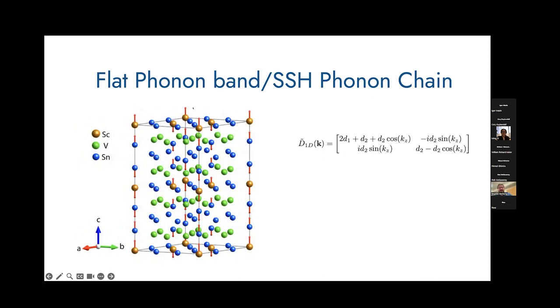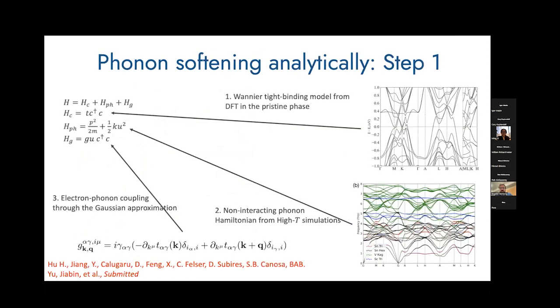Okay. After. So the model here is that of an SSH chain, basically. So it's very flat in plane, but it's got SSH couplings out of plane. And the phonon, as you can see, is at momentum pi, and is the even phonon with respect to the unit cell in plane. So it's the even wave vector. So now, in order to understand the softening of the phonon, we must get a handle on the electron-phonon interactions.